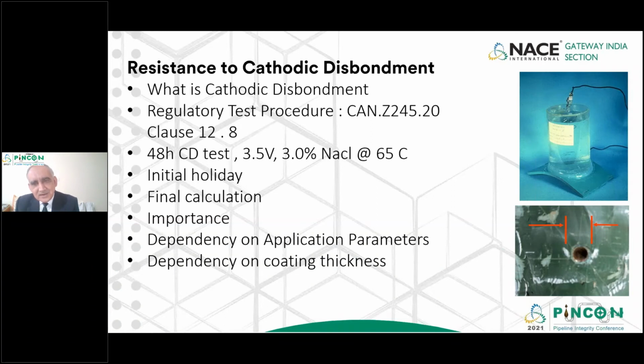After 48 hours, this assembly of beaker and all is removed. The panel is allowed to cool down to room temperature, and then a knife is used to remove the coating. In case this whole accelerated process has crept inside the coating and affected the adhesion of the coating, then the coating comes off with the knife. Otherwise, it will resist. And then finally, a measurement is done of how much coating was removed, and that is a measure of adhesion for the coating. This is called resistance to cathodic disbondment.